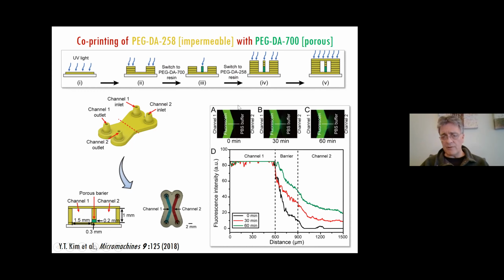And we verified that as you fill one of the channels with fluorescein, you would end up having fluorescein on the other channel by diffusion. So that's something that you could of course build by PDMS with several layers and so on. But the elegance of this approach is that it only takes an untrained operator to switch the resins, and the whole alignment of these layers is done by the program.